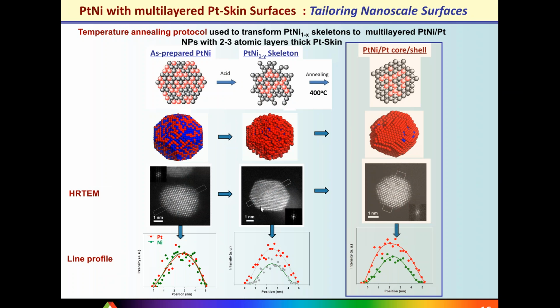So what we were aiming for is something like an ideal type of skin. And here our intentional dissolution of surface nickel was leading to a skeleton type of surface, and then after annealing we were looking into particles that were much smoother in terms of morphology, but at the same time they kept a very desirable surface compositional profile, and the thickness of that layer was at least 2 monolayers. So that was extremely important, not only to achieve high activity, but also to address durability issues.